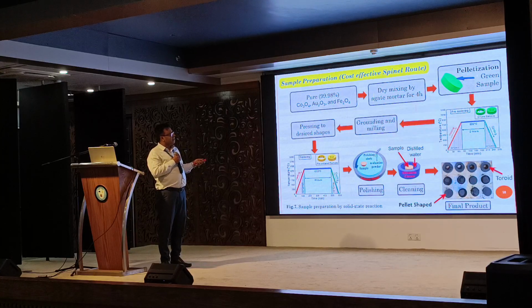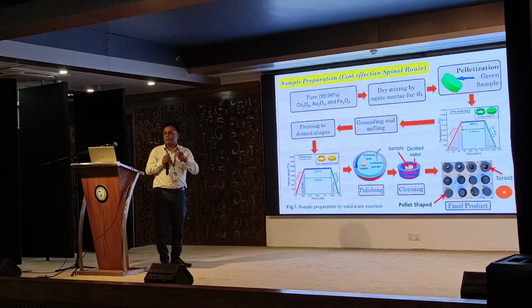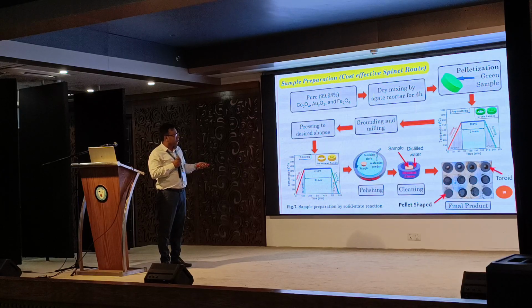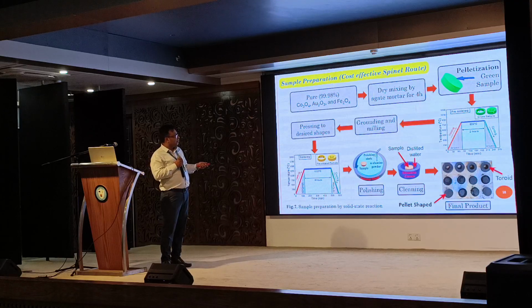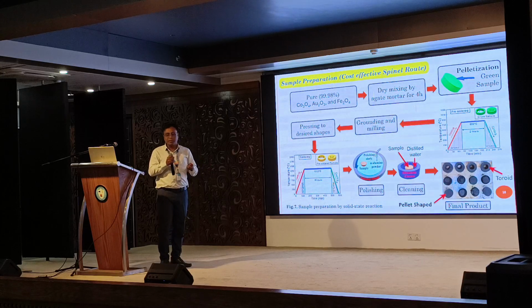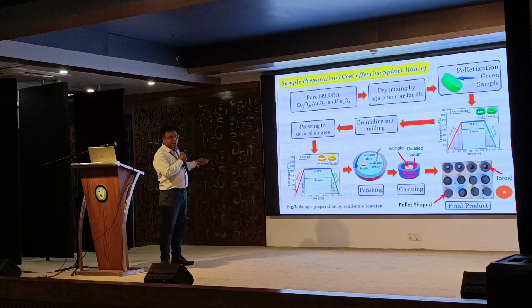After making the pellets, we perform the pre-sintering. This is preliminary sintering. That means we apply heat at 10 degrees Celsius per minute and keep it inside the furnace for 2 hours at 800 degrees Celsius. Then furnace cooling. Then again we grind that pellet, grinding for 4 to 5 hours. Then again pressing to the desired pellet shape.